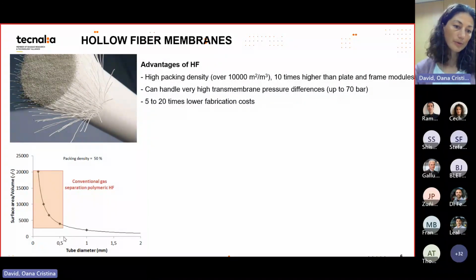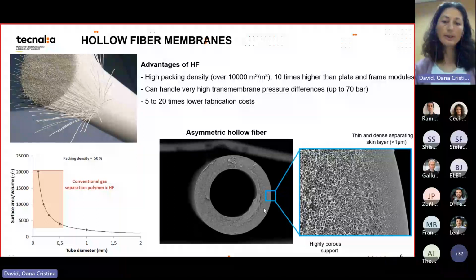So when the outer diameter of the fiber becomes lower than 0.5, then there is an exponential increase in the membrane area you can pack inside the tube. And this is one of the advantages of this geometry. And this is called packing density. So the square meter of membrane area divided by the volume of the module where you place the membranes inside. Normally, they can also work up to 70 bars. This is also important.